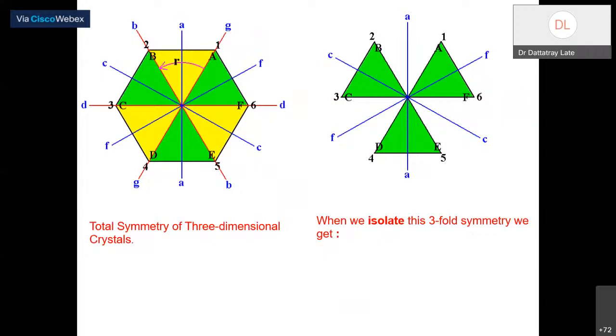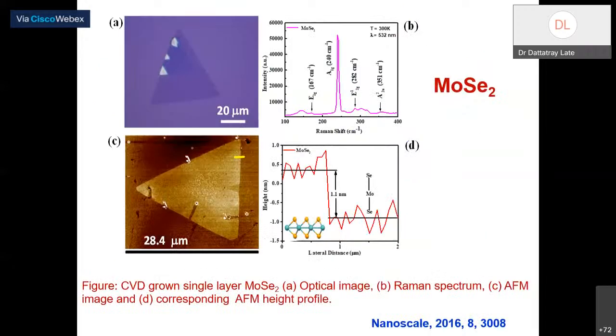Again, I'm getting 3-fold symmetry because 3-fold symmetry is very much dominant as compared to bulk material, because in bulk we have 6-fold symmetry. So 3-fold symmetry is very much easy. The energy required to have a 3-fold symmetry is very less as compared to 6-fold symmetry. So I'm always getting a triangular shape, because the triangular shape, that is nothing but a 3-fold symmetry, is much easier, because very low energy is required. Therefore, I'm always getting a triangular shape.